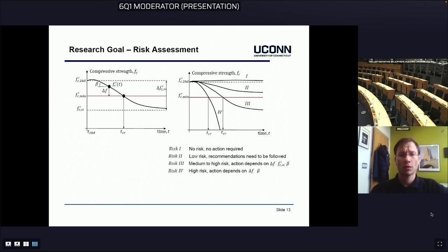And so a base concept of our research in terms of the risk assessment is placed on the structural integrity of the walls, or in general of the material, which is based on the compressive strength. We start with a certain amount of strength which has been cast in those walls, but then there is a minimum strength required for structural integrity, shown here by the red line. If we have deterioration going on, could it be through cracking or through the development of thaumasite eating up the strength from the CSH phase, then the strength goes down, and at some point it might go below the minimum strength requirement. This would be the critical time where we would need to determine that those foundations, for example, need to be replaced.